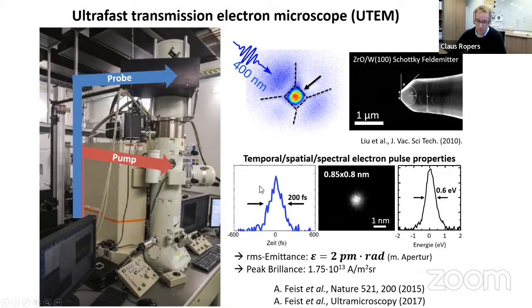Okay, so here are some typical specifications that can be achieved in this microscope. The electron pulse duration is down to 200 femtoseconds or slightly shorter, and you can focus this electron beam, as with a regular electron microscope beam, down to sub-nanometer dimensions. And you also have decent kinetic energy resolution. So essentially, what this constitutes is a nanoscale local probe of structure and electronic excitations, as far as that's possible in the electron microscope, with sub-nanometer spatial and sub-picosecond, few hundred femtosecond temporal resolution.